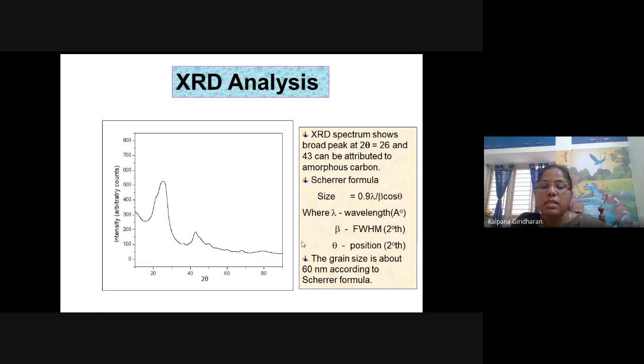This is the X-ray spectrum. From the Scherrer formula, we found grain sizes about 60 nanometers.